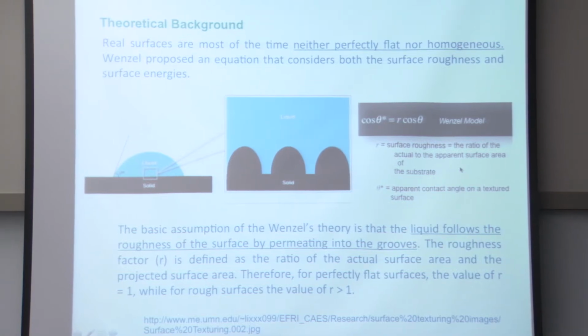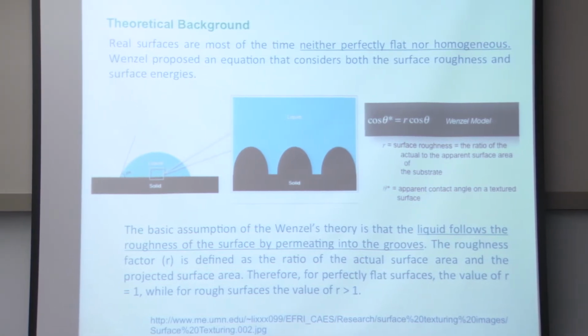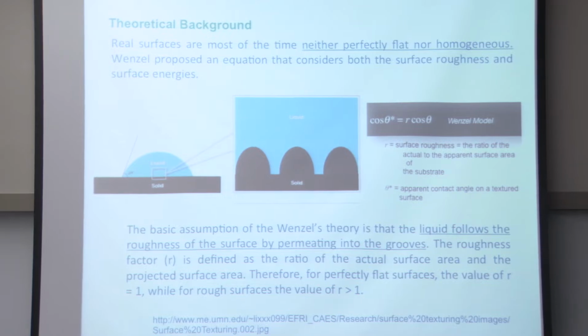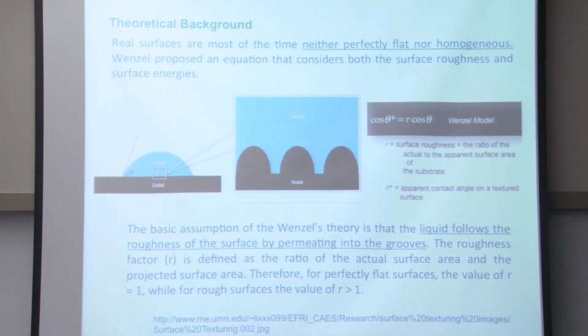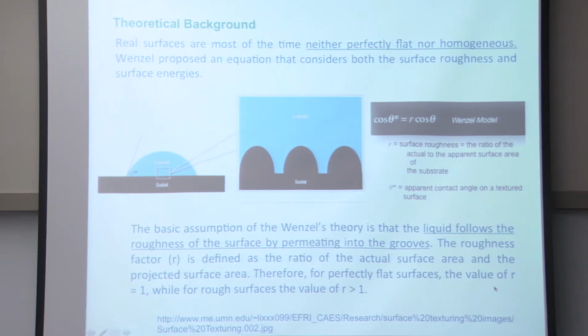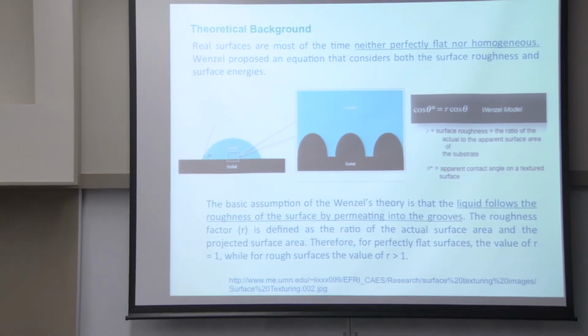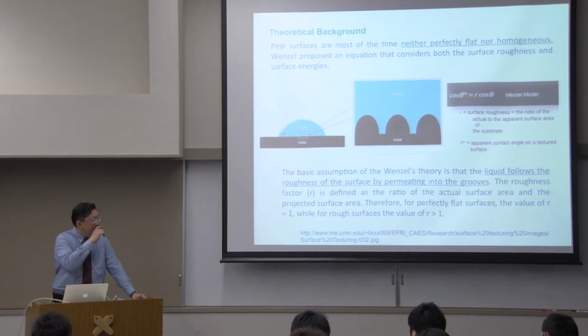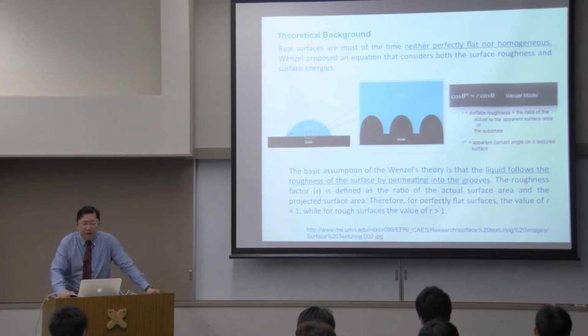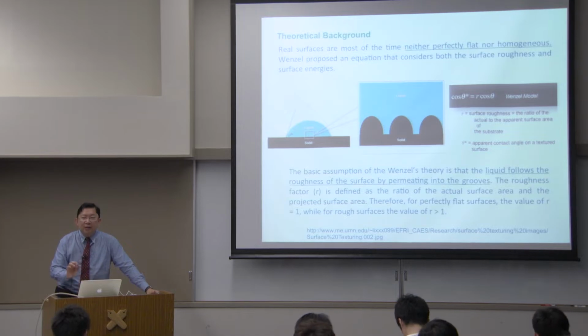This correction is important because you have to accommodate for the change in surface area. The roughness is defined by the actual surface area and the projected surface area. So if you have a value of R equal to 1, then there's no correction. But if you have an R value greater than 1, then there is definitely a surface effect based on the Wenzel correction.